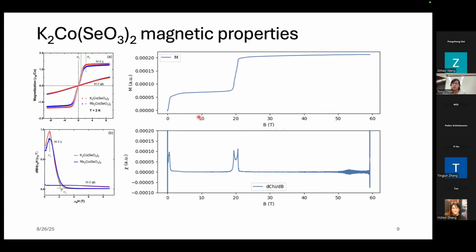But we have temperature dependence of this measurement. We measured at a couple of different temperatures, but we could not track the trend of these two peaks, which might be because there are some magnetocaloric effects happening here. When you change the field rapidly, the temperature of your sample also changes. And that's a characteristic of a supersolid as well.